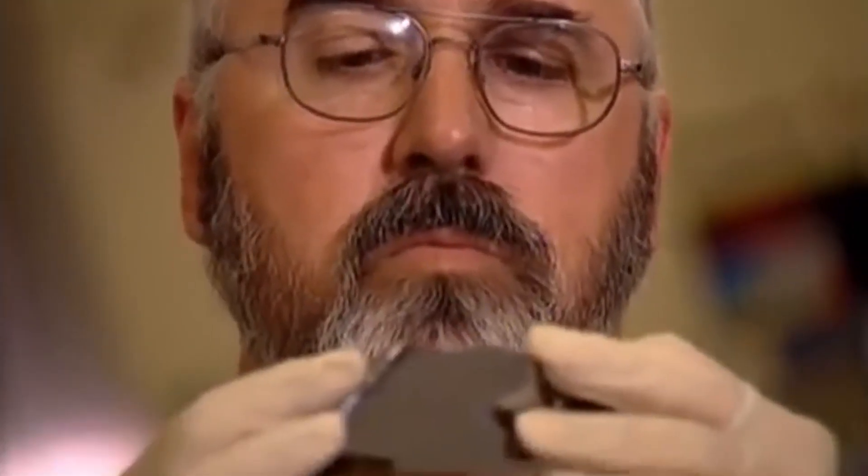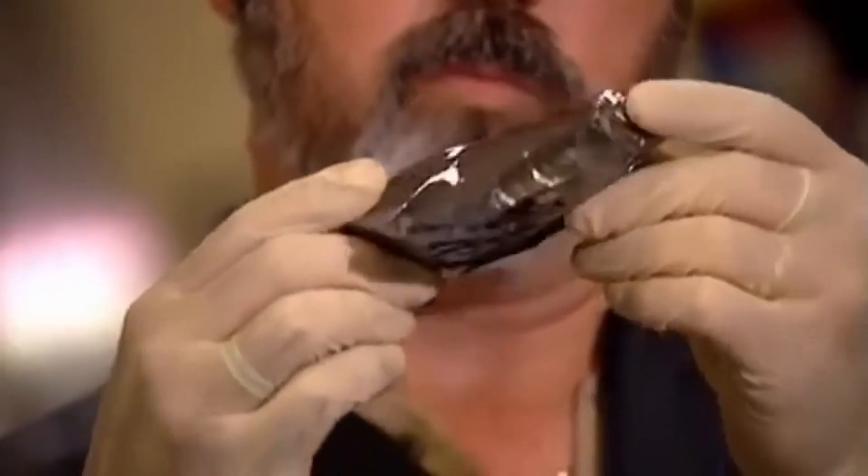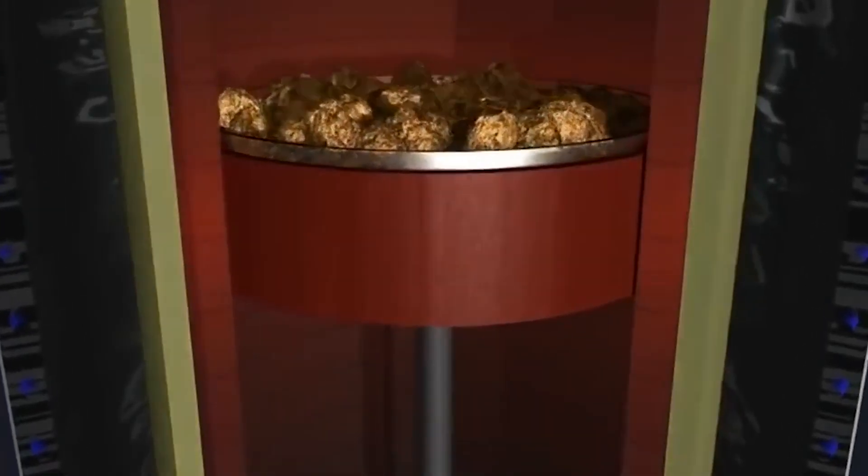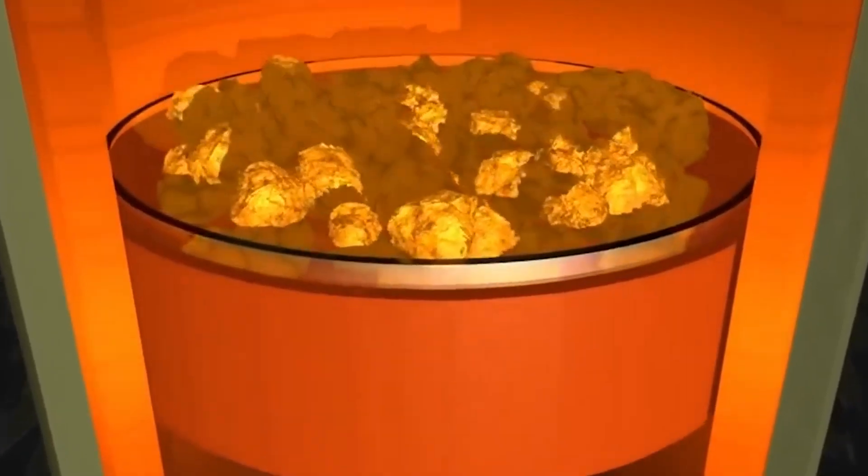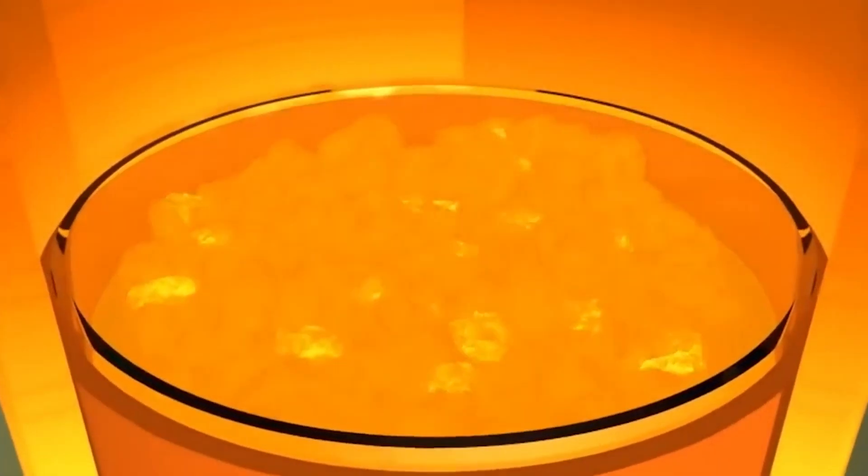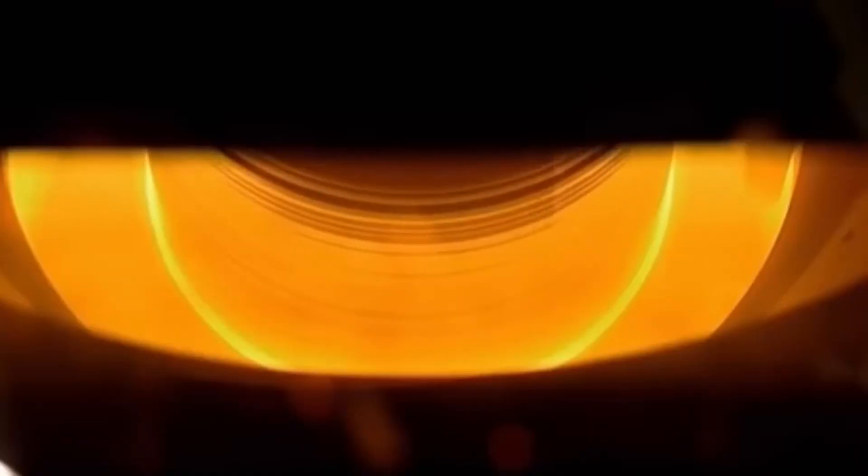A large monocrystal is extracted from the purified silicon melt. The process starts with polycrystalline silicon heated to about 1,420 degrees Celsius inside a special sealed furnace. This furnace has been purged with argon gas to remove the air.